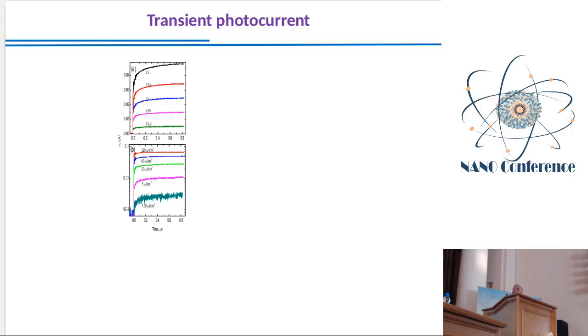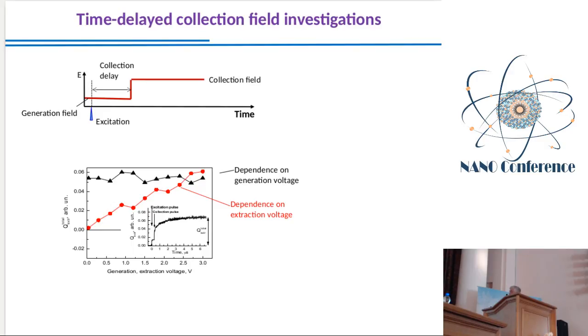Okay, so here is the transient photocurrent dynamics. When we increase excitation intensity, this slow part almost disappears, so only the very fast photocurrent component remains. This is understandable because in this case nonlinear effects take place, like exciton annihilation and also fast charge carrier recombination. So in these measurements we cannot clearly separate two processes.